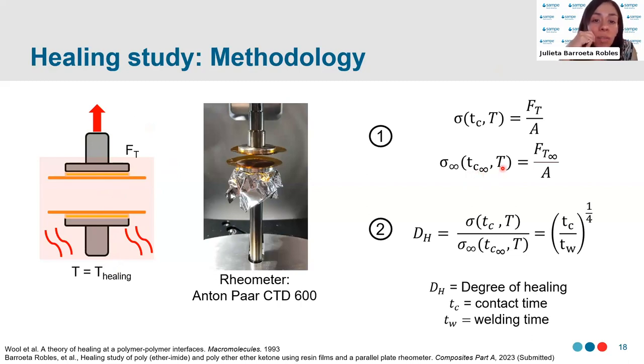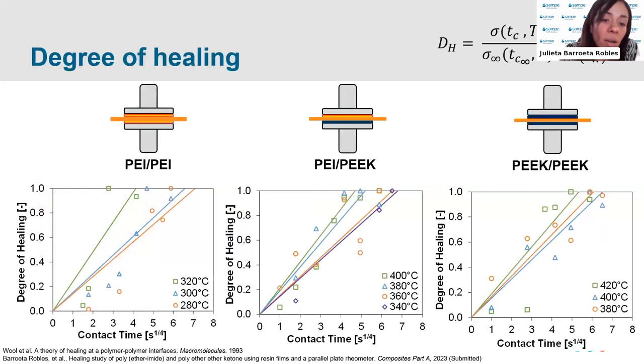Following the healing theory and the reptation theory, by normalizing, by taking the ratio actually of these two numbers, we can obtain a degree of healing and relate it to a contact time and to the welding time. Now, by keeping this in mind, if we plot this number, we can obtain graphs that look similar to what I'm showing to you in the slide. By plotting the contact time on the x-axis and the degree of healing on the y-axis, and by taking a linear regression of the points and calculating the slope, we can get the welding times.